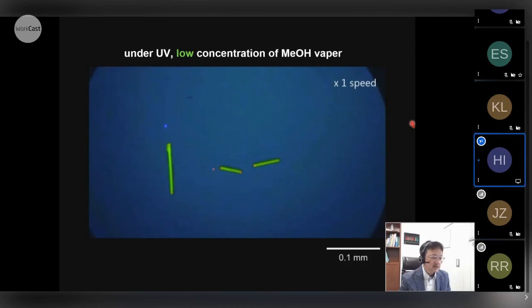But my student cut this crystal with a knife. And as you can see, you can find the growth of the green part, just at the part of the cutting of these crystals. After several minutes, this green part disappeared and the whole crystal changed to an orange color. And in this crystal structure, methanol was maybe released. This crystal first has methanol inside the crystal, but the mechanical stimulus can trigger the release of methanol. This is the reason for this color change.